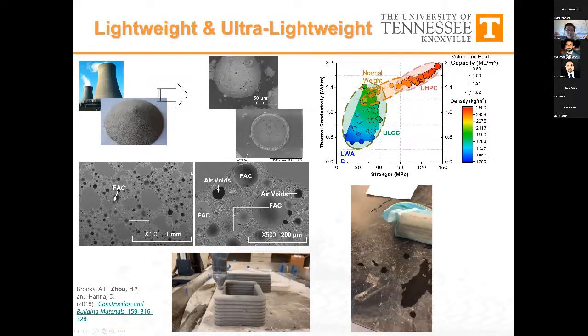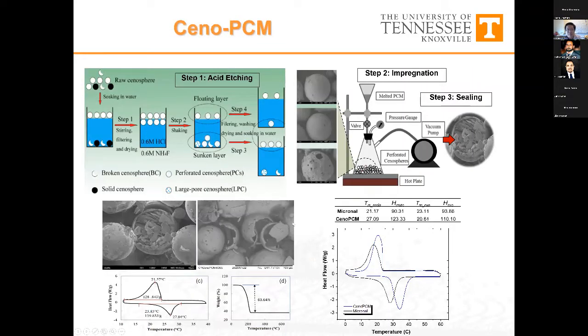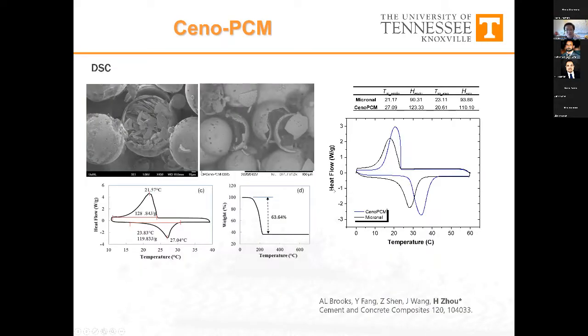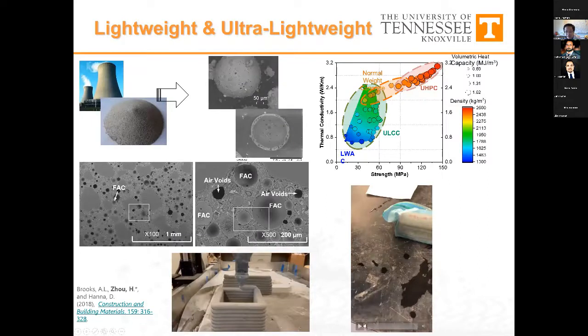One thing that we are currently working on is a different encapsulation technology where we use fly ash cenosphere, which is a hollow part of the fly ash, as an encapsulation shell. This is a project that we have in collaboration with University of Alabama, to use as a capsule to hold PCM materials, and that can be incorporated into 3D printable mixtures. So I just want to show some preliminary thermal test results.